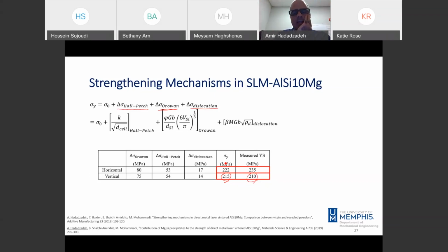Yeah. So for the case of the horizontal sample, there is a difference between the measured and predicted value, 222 MPa and 235 MPa. The difference between these two values is about 13 MPa in this case. And if we look at the strength increment coming from these dislocations, it is 17 and 14 MPa. So this 13 MPa is in the range of strength increment coming from these dislocations. So it's somehow significant.